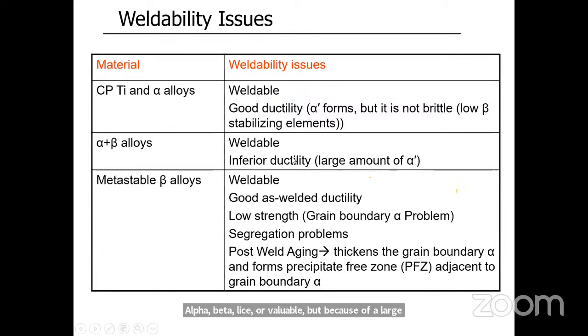So these are generally the weldability issues for different titanium alloys. CP titanium and alpha alloys are generally weldable and give good ductility also. Alpha-beta alloys are weldable, but because of a large amount of alpha prime martensite, ductility will be less. And metastable beta alloys are weldable, with good ductility as well. But when you do aging, grain boundary alpha will form. That is a problem. Strength will increase, but ductility will drastically decrease.